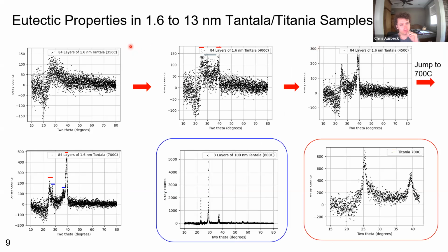So we also see eutectic properties in the 1.6 to 13 nanometer tantala/titania samples. And the best case of this is 84 layers of 1.6 nanometer tantala. As you can see here at 350 C, this 1.6 nanometer tantala sample is still amorphous. However, once we go up to 400 C, we see something very odd appear. So we see these 2 peaks here, these 2 red peaks, if you can see them.